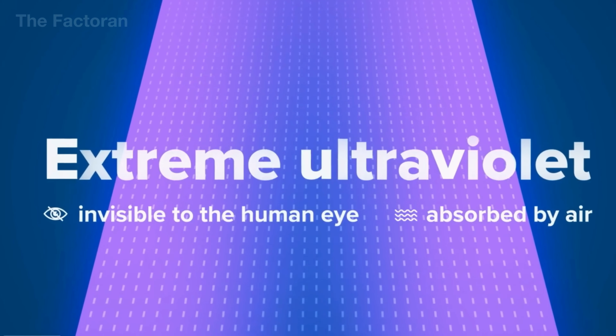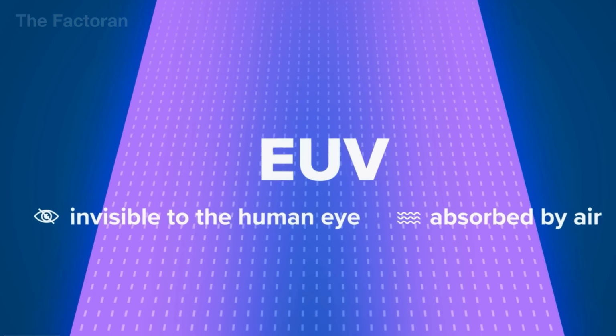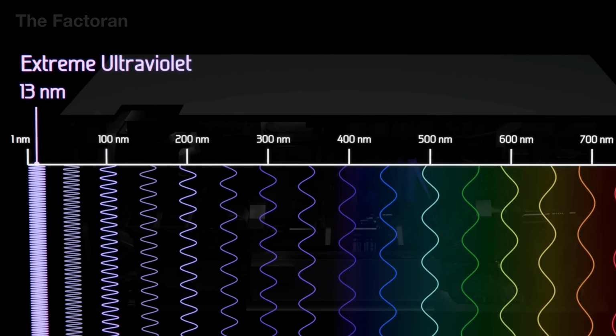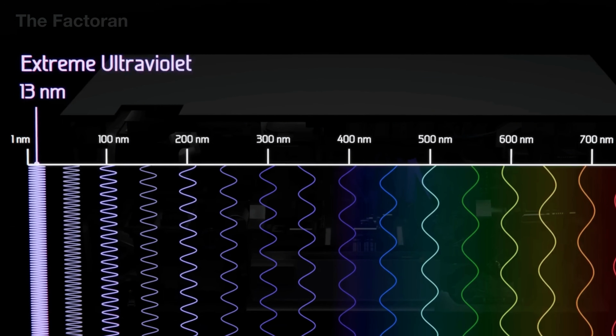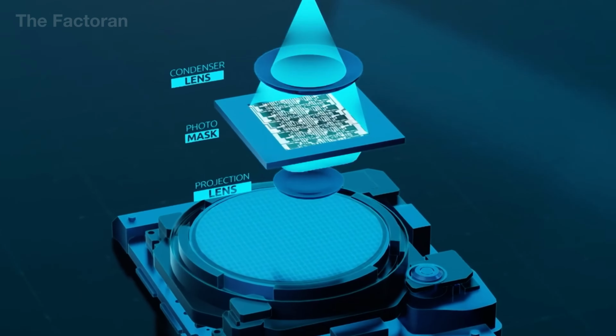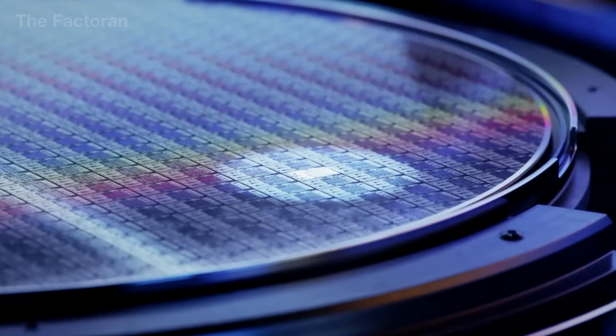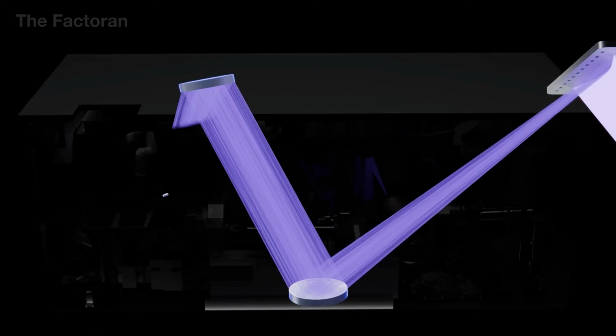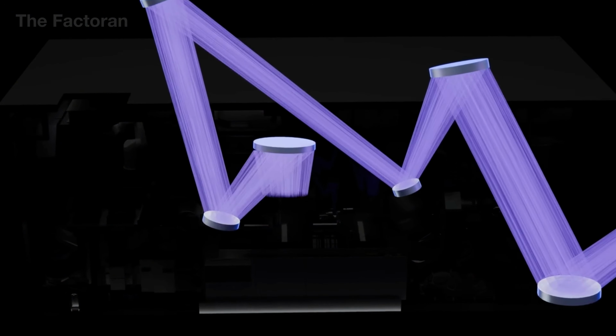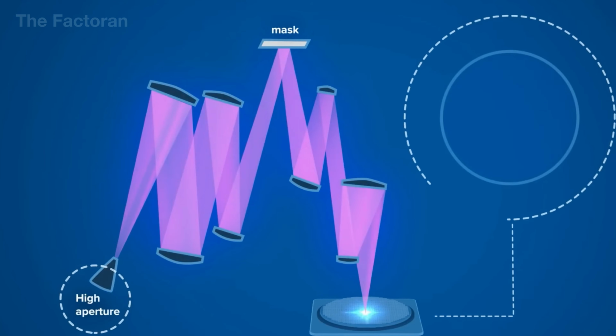The light used is EUV, with a wavelength of 13.5 nanometers, generated by firing 50,000 tin droplets per second into a vacuum chamber and turning them into plasma at temperatures approaching 500,000 degrees Fahrenheit. At this energy level, light cannot pass through conventional lenses, so the system relies entirely on multi-layer reflective mirrors with surface precision smaller than an atom to guide the beam.